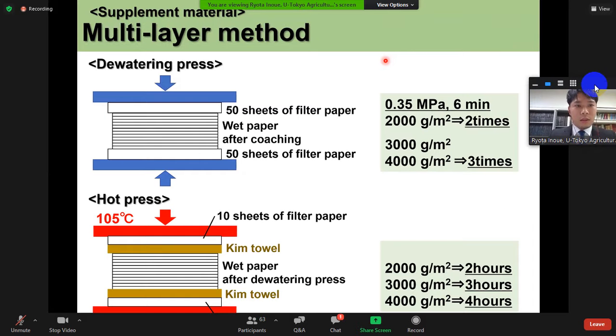So I'm asking you instead of the audience, how did you prepare multi-layered paper? Only stacking dry sheet or then pressing at 105 degrees Celsius? No re-wetting. Please answer this question. Okay. Multi-layer method is this. First, after couching wet paper, dewatering press multi-layered, and after dewatering press, we use hot press at 105 degrees. Is that okay? Okay, maybe okay.